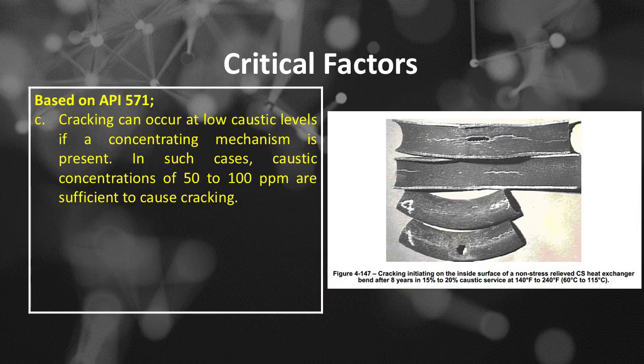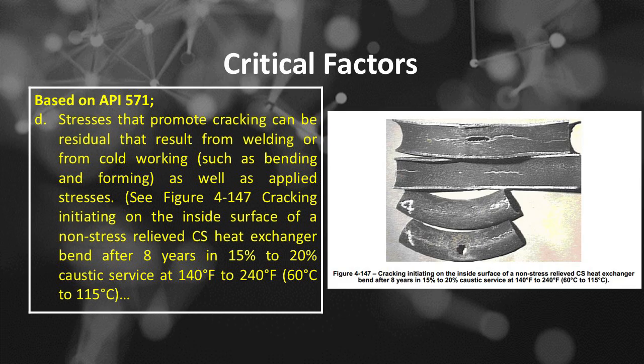Number C, cracking can occur at low caustic levels if a concentrating mechanism is present. In such cases, caustic concentrations of 50 to 100 ppm are sufficient to cause cracking. Number D, stresses that promote cracking can be residual stresses that result from welding or from cold working, such as bending and forming, as well as applied stresses. See Figure 4-147.